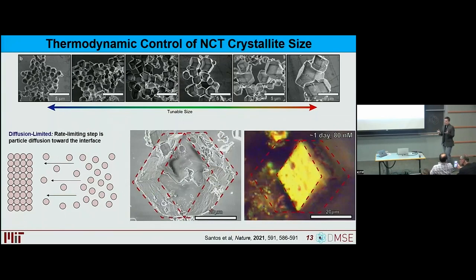I don't think this is the largest crystallite. I think Chad beats us by a factor of about 3 or 4 at this point with the paper he published recently. But the key thing I would point out is this 50 or so micron crystal was made in just a day. So we can actually study a lot of these materials at much larger length scales than we typically could via sort of this rapid assembly process.